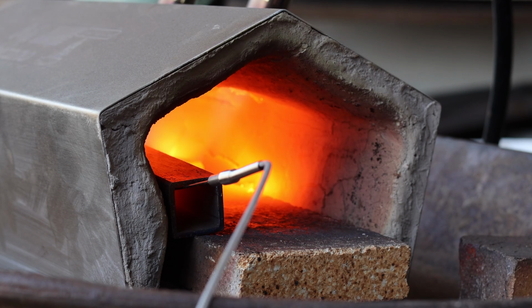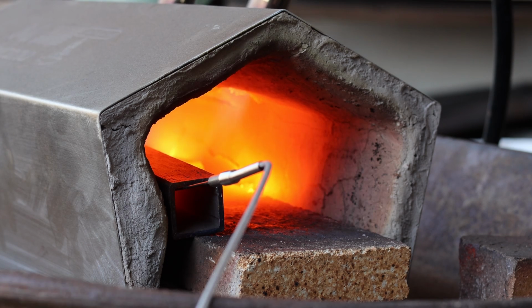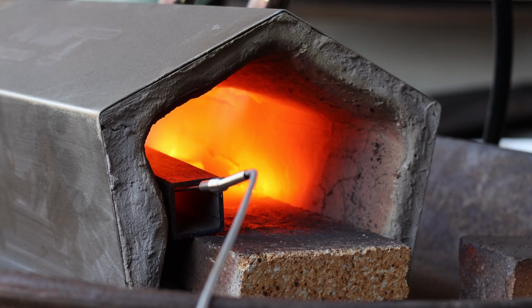What I've done here is I've got a thermocouple measuring the temperature at a certain point inside that square tubing. That square tubing is kind of minimizing the effects of having the pinpoint heat from the burners and trying to spread that out a bit more. And I've got my forge ramped down about as far as I can get it without it dying. Now the tip of the thermocouple is sitting right about 1650 Fahrenheit, and that's the temperature I need to hold my knife blade at for about 10 to 15 minutes for the first